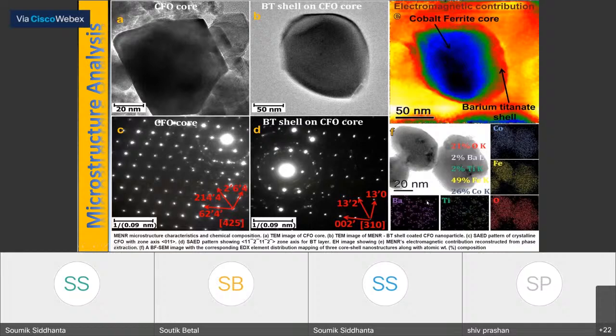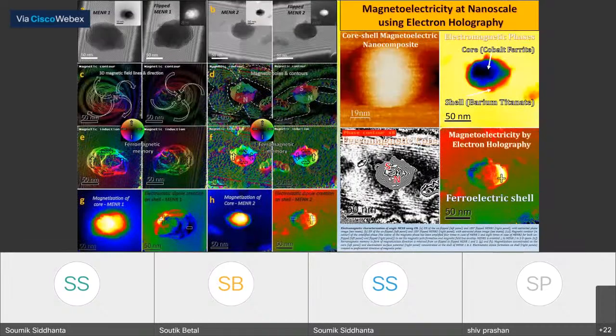Lastly, the EDS measurements show that the cobalt ferrite, in our fabricated device, is all confined at the core, whereas the barium and titanium are spread throughout the shell of this structure. Now here comes the electron holography method, which is a very new technique, and seldom have papers explained it.